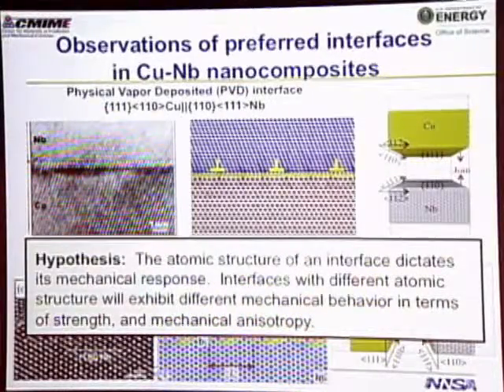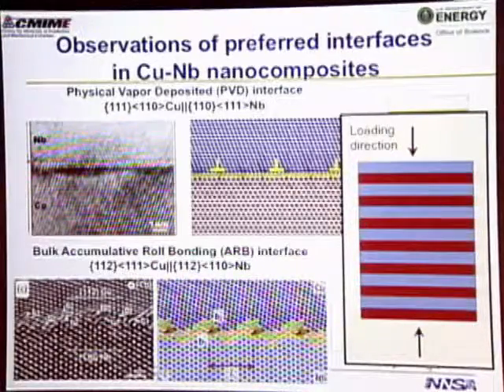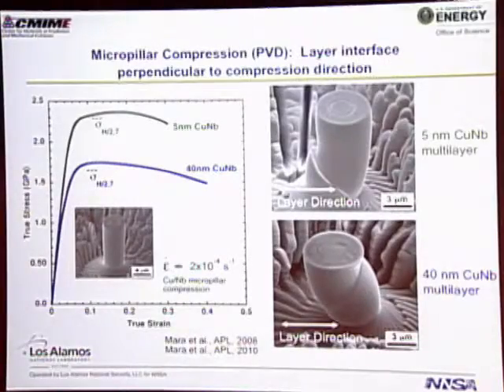So we can revisit our hypothesis using these two different types of interfaces. So what we're going to do first is squish this material in this direction, perpendicular to the interfaces, and see what happens. Now we're going to use a technique called micropillar compression. Why it's called that is if you look at the diameter of these deformed pillars, this is only 3 microns. A human hair is approximately 100 microns. So this is about 30 times smaller in diameter than a human hair. We can do these tests using specialized equipment. You'll actually see some videos of ones that we do in the electron microscope.